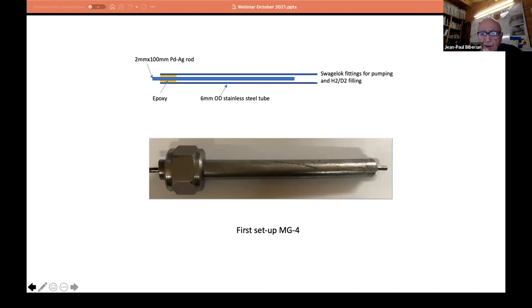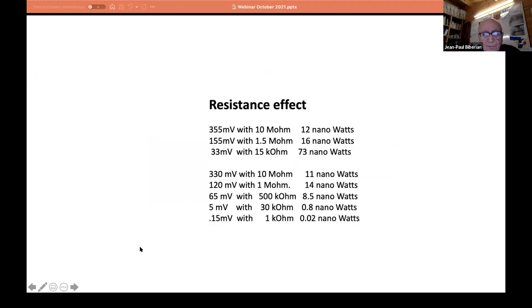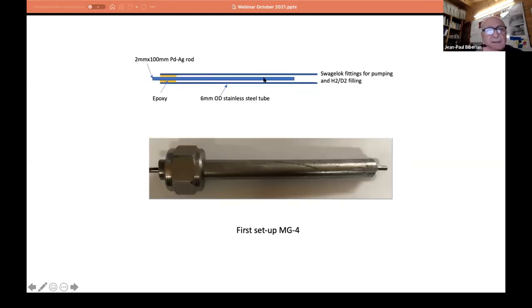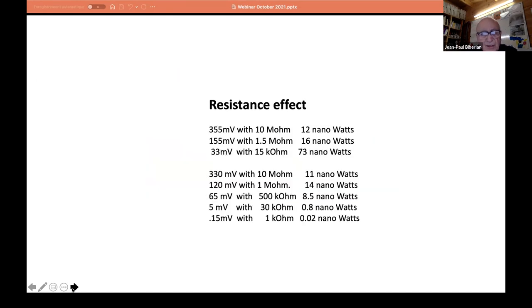I had this 2 millimeter palladium silver rod. In the first experiment, I used this rod without any deposition on it. Then I put hydrogen inside, but there was no excess heat whatsoever, no electricity whatsoever. It was zero. So I decided to change something. By electrolysis, I deposited palladium on top of this rod. Once I had deposited palladium on the rod, then very suddenly when I measured, there was electricity coming out.